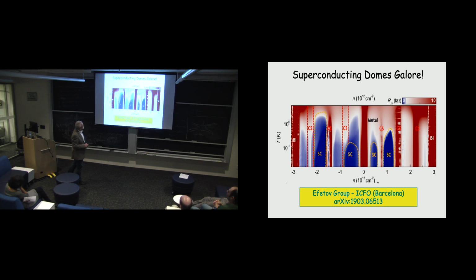The difference in density between this insulator and this superconductor, as indicated by the resistance and the temperature dependence of the resistance, which I'm not showing to you, is a density of about 1 electron for every 10 to the 5th carbon atoms. So this is impressive in terms of what the quality of the samples must be. And the superconducting transition temperatures are bigger than aluminum, so real superconductors.